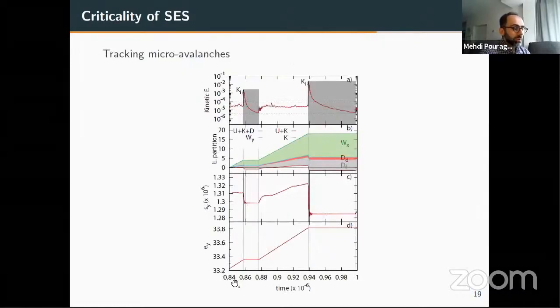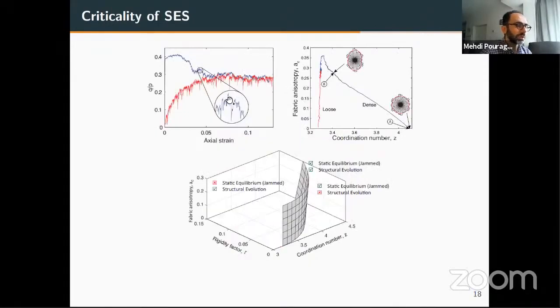Okay. So what we did was a quasi-static simulation. At the bottom, you see the driving vertical strain. We start driving at a constant rate, and as soon as a threshold for the kinetic energy of the whole sample is reached, we call that the beginning of a micro avalanche, and we stop loading to separate all the events as best as we can. We let the avalanche dissipate, and when a lower limit is reached, we start loading again until we reach a second avalanche. You see the partitioning of the energies, and what we are seeing here is basically a zoom into two of these events.